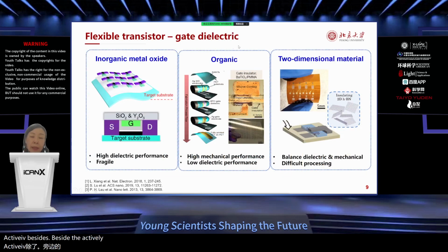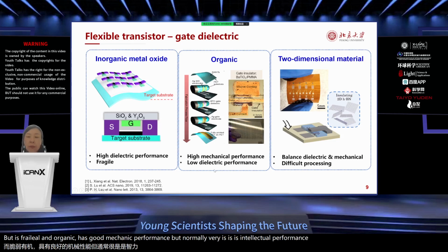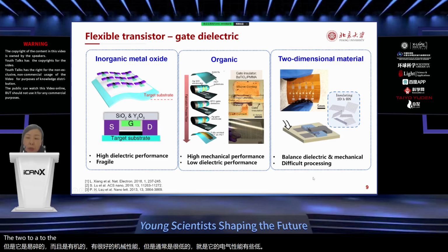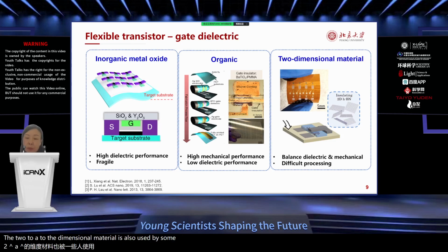Besides the active layer, the gate dielectric is also a bottleneck to realize soft electronics. Normally, people have two choices. One is inorganic metal oxides. That one normally has a good K value, so it has a good capacitance value, but it's fragile. And organic has good mechanical performance, but normally its dielectric performance is somewhat low. The two-dimensional materials are also used by some of the researchers. It's a balance between dielectric and mechanical performance, but forming a very good layer of the 2D material is not easy, especially for flexible and stretchable devices.